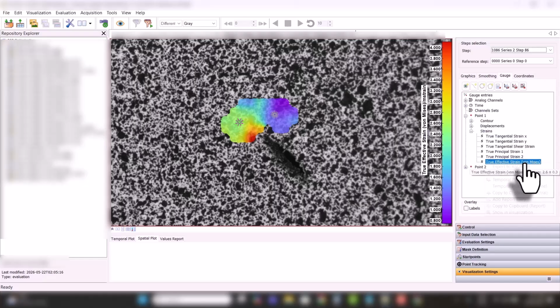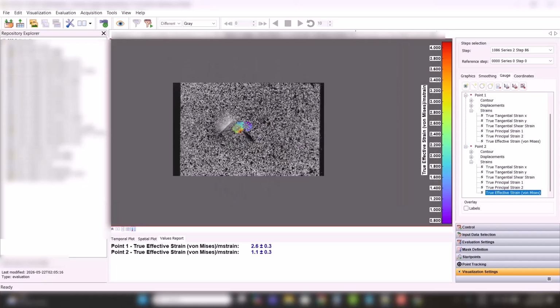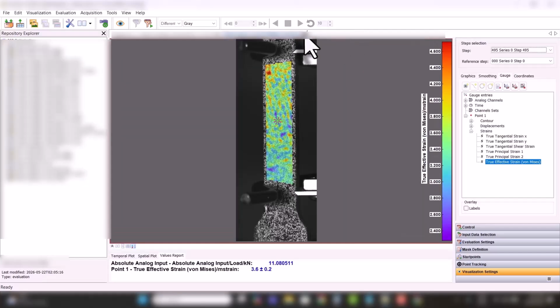If you look at the value, this has a precision of 0.3 millistrain. So that's solid. This one, 0.3 millistrain. So again, you'd use your MATLAB code to append any points that aren't currently in your main field onto your full text files, and then plot the full color scale results using MATLAB.